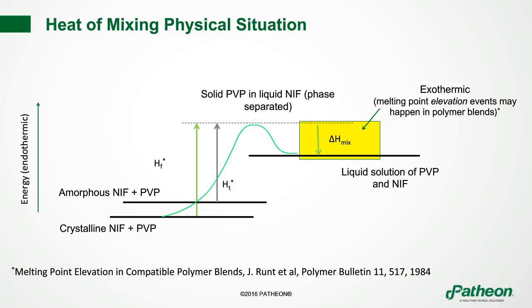But then what might happen is that you actually see a decrease in the overall energy state, because as they mix, energy could be released, and that would be an exothermic event. Now, what we can actually measure using differential scanning calorimetry is the energy required to go from the ground state, which is crystalline nifedipine, PVP, up to where you see the liquid solution of PVP and nifedipine. We don't measure the energy it takes to get to the dotted line. We measure the energy it takes to get from the lower solid line to the upper third solid line, which you see the yellow box is pointing to.